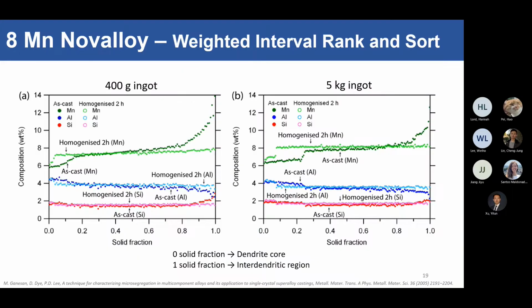So what we did was an EDS grid scan across the same microstructure, and then we arranged the data using this weighted interval rank and sort system, WIRS. Right, so let me explain. Solid fraction of 0, that's the dendrite core, the center of the dendrite. Solid fraction of 1, that's the interdendritic region then.